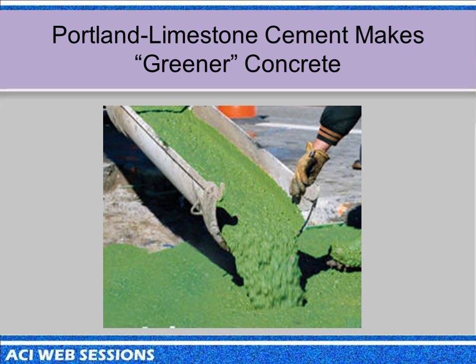If you start adding fillers and recycling fillers into the system, the quality of the limestone does impact the performance. We've seen that from a number of studies in Europe, which is why we included the quality requirements in the limestone. There's all kinds of possibilities out there, but one of the things that concerns me in Europe is there's a lot of use of limestone fillers for self-consolidating concrete going into cold foundations, and they just haven't addressed the thaumasite issue there. And I think that's why we're trying to address it up front and prevent it from happening. There's nothing like a failure to stop a product from being adopted in the market. Thanks very much.